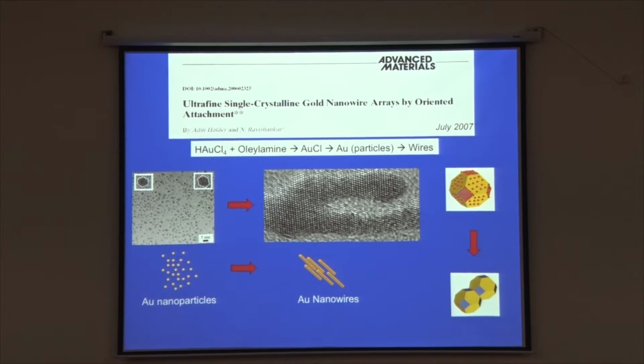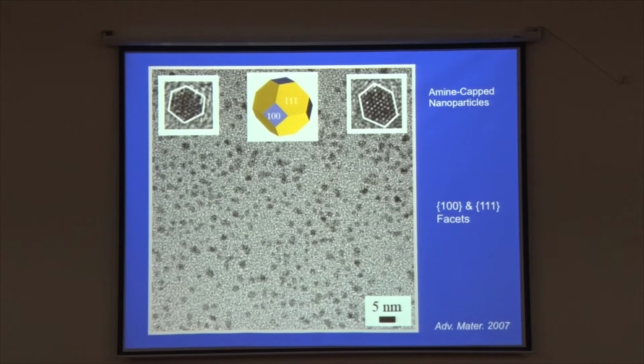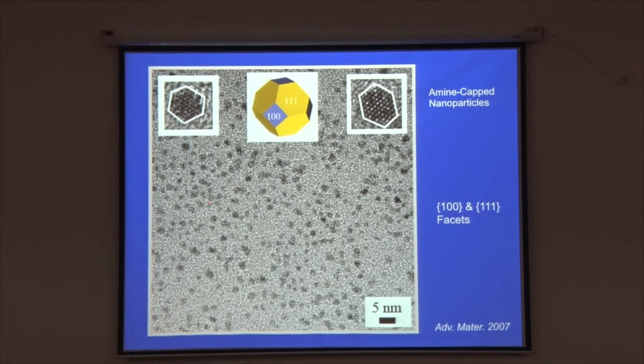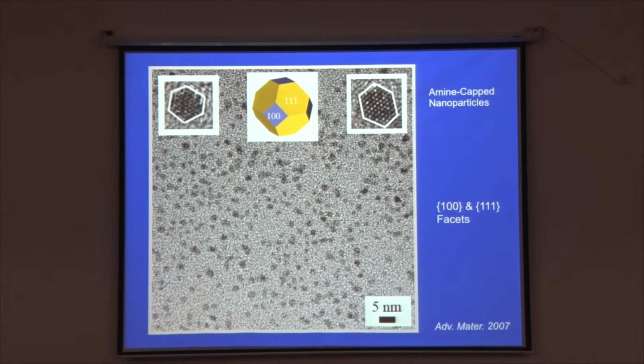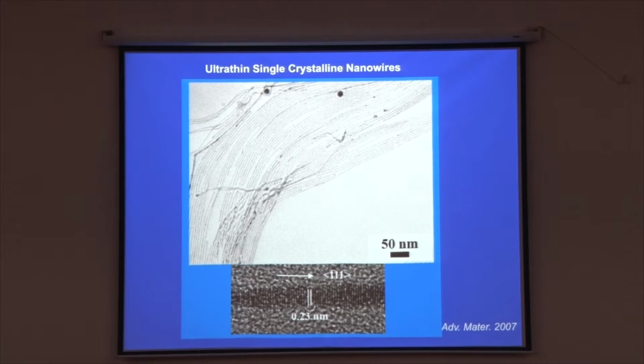This I call dimerization. This dimerization is actually the first step of the symmetry breaking that happens. I will explain in more detail what happens. So, this is our starting state where we have very fine particles, and in the transmission electron microscope, if you look at these rightly oriented particles, we can see that they have this shape. Okay. And after the so-called oriented attachment happens, we end up with these very long, thin, single crystalline wires, as is evident from the high resolution image. What is happening here, and what is the symmetry breaking?